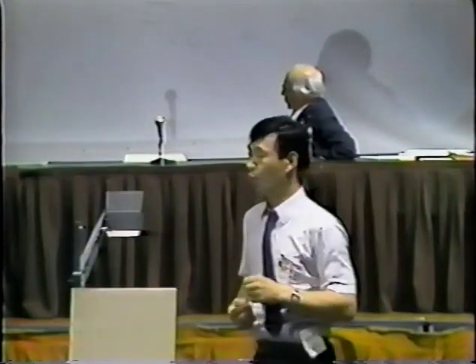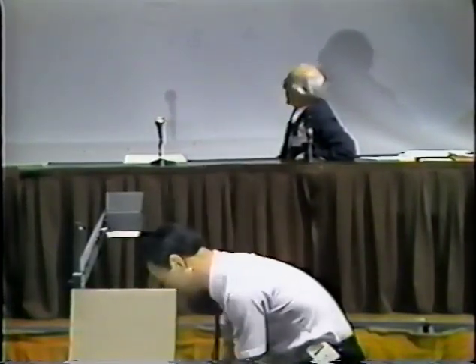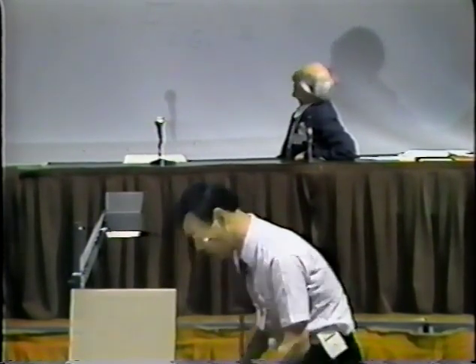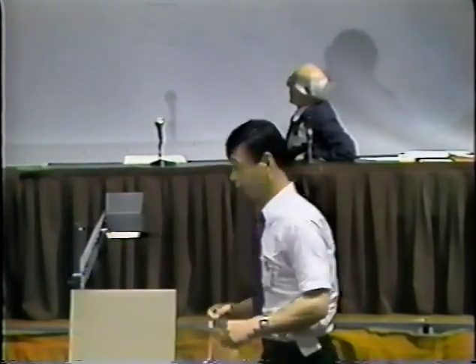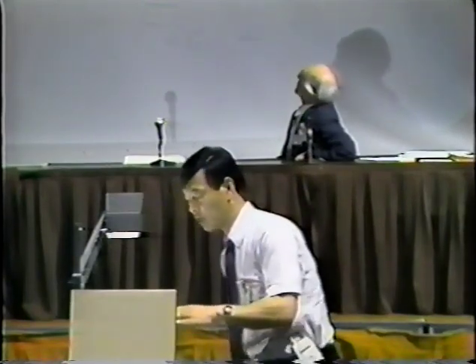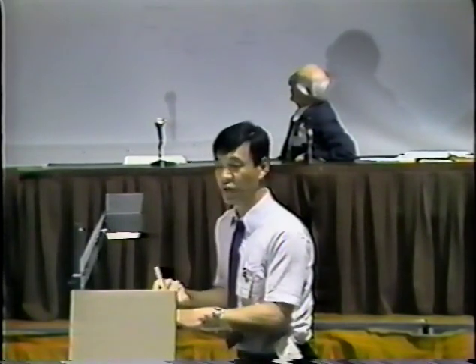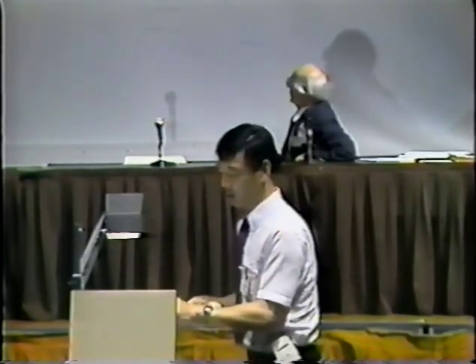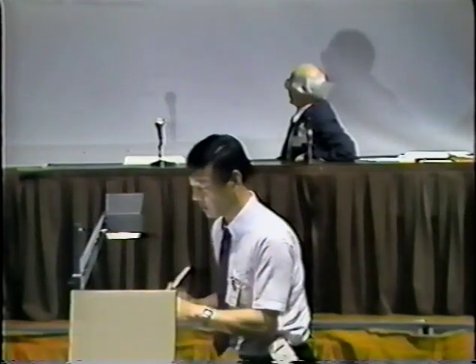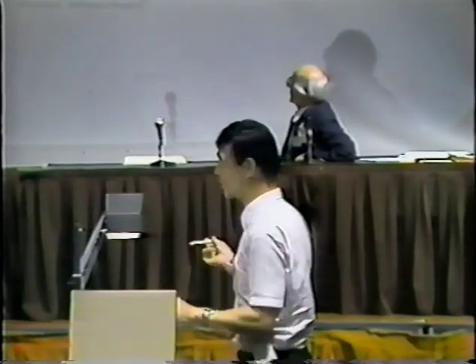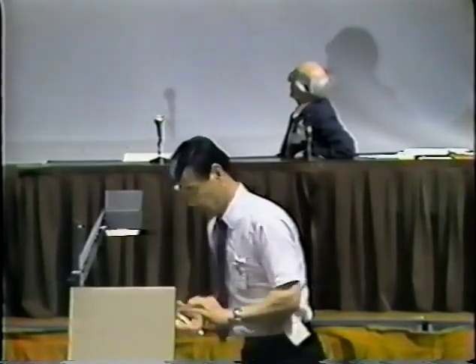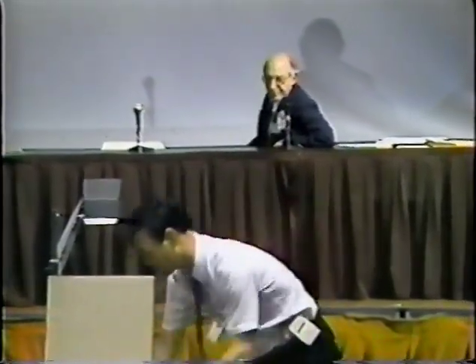diffused into the palladium, and from the same scattering data, we know that the ratio of deuterium to palladium is very close to 1 to 0.8. So one thing is you should be careful to keep the palladium out of water or something, and one method of putting in a lot of deuterium gives this, still 0.8, so it's not enough to make more than one, but anyway, you can make some sort of things here. And what's the ratio you have? I would say 0.8 plus or minus 0.1.